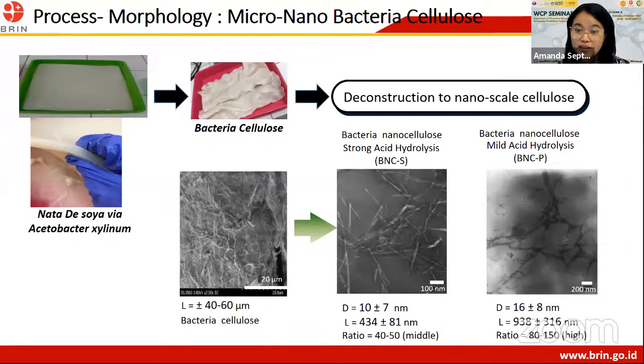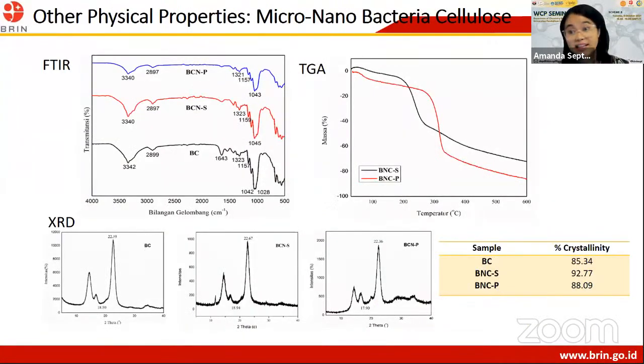Interestingly, the bacterial nanocellulose is generally showing a longer aspect ratio than the plant-based nanocellulose. In terms of crystallinity, it also has a higher crystallinity, perhaps due to the higher purity of the cellulose, without any lignin and hemicellulose content inside the bacterial cellulose.